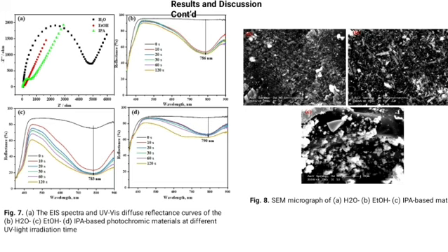And in addition, the UV-visible reflectance spectra of the materials demonstrated broad reflectance peaks at 784, 783, and 790 nanometers, which correspond to the water, ethanol, and isopropyl alcohol-based heterostructures at different irradiation times, revealing 59% reflectance, 32% reflectance, and 22% reflectance for the different materials. This result could imply that the absorption of energy responsible for the excitation of photons emitted to the external environment is highest in the ethanol-based material. Thus, it could absorb and reflect more light energy.